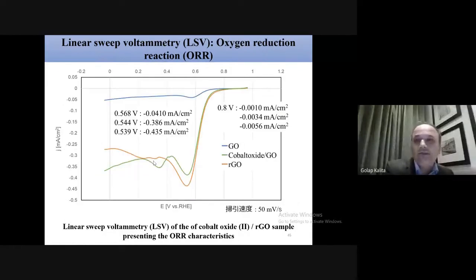Then if you see the ORR, oxygen reduction reaction, for the graphene oxide and cobalt graphene oxide it is quite less, but for RGO and cobalt oxide RGO, the onset potential is coming around 0.8. This is also in the RHE scale. This is almost the same for RGO, and both samples have almost similar ORR activity.